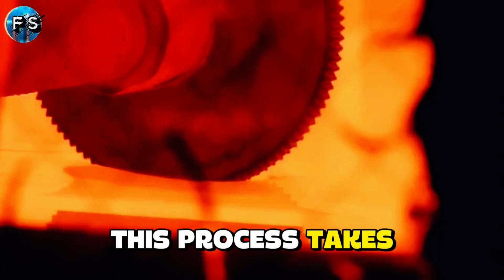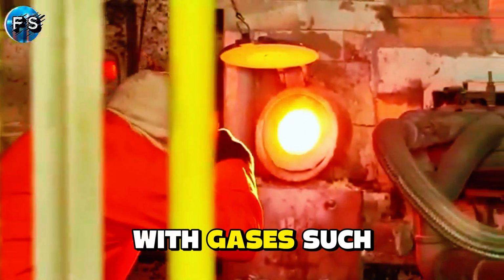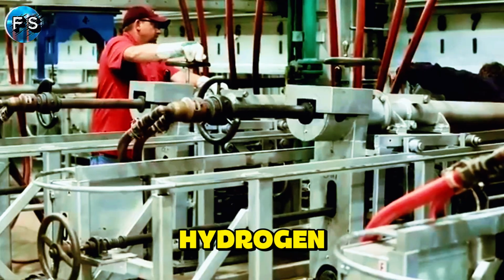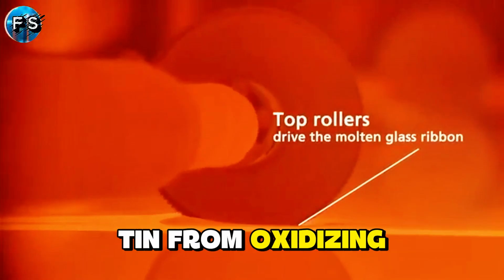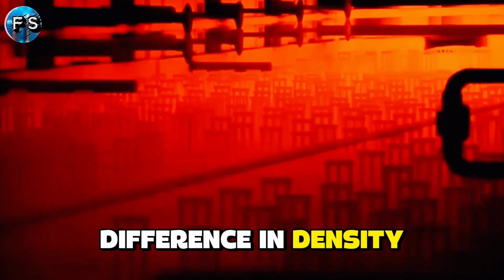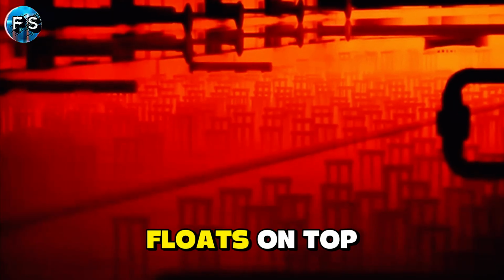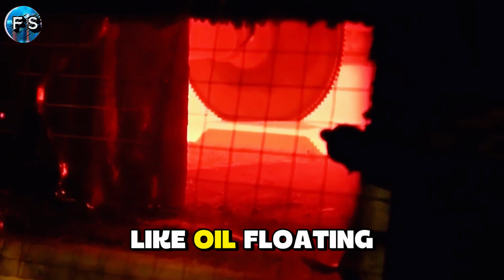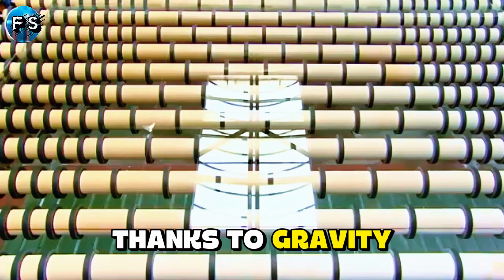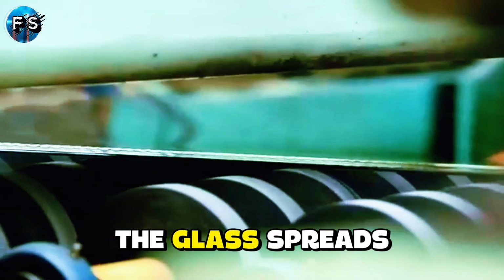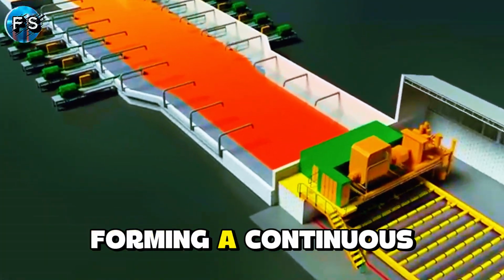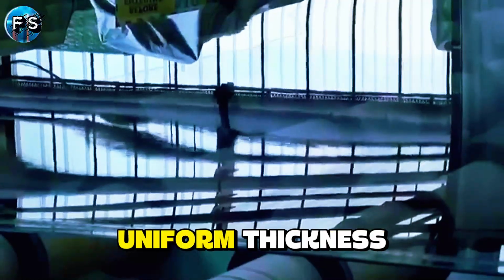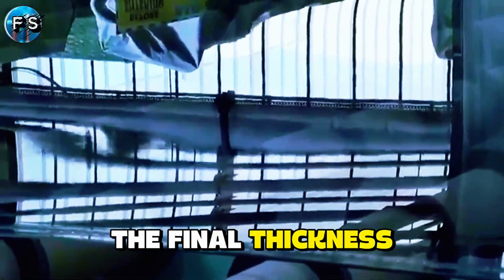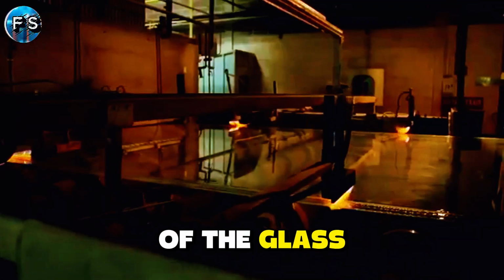This process takes place in a protected environment with gases such as nitrogen and hydrogen to prevent the tin from oxidizing. Because of the difference in density, the glass naturally floats on top of the tin, like oil floating on water. Thanks to gravity and surface tension, the glass spreads evenly, forming a continuous, smooth sheet with uniform thickness. The final thickness can be controlled by the speed of the glass movement.